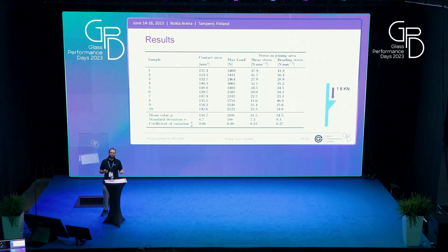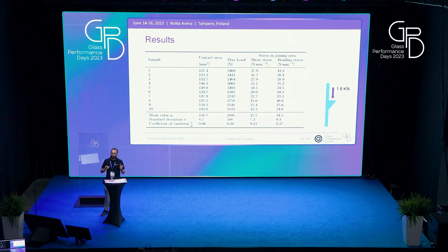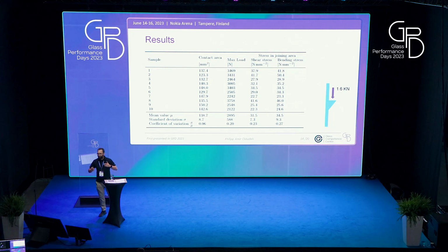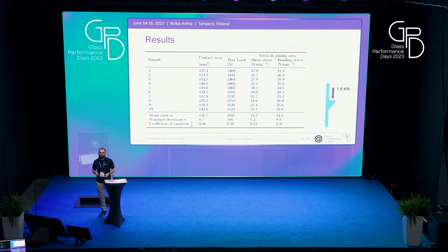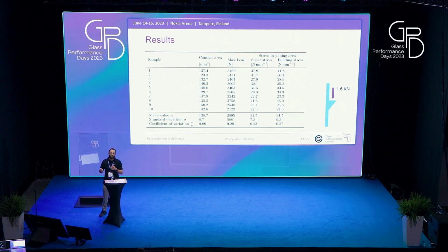So we are in a range where we can say yes, we can apply load on an AM glass component into a glass plate. So we could say now, okay, this can transfer 1.8 kilonewtons. This is better than silicone or glued connections, but it's difficult to say if we don't understand the crack pattern, and we also know that silicones or other connections also have advantages.